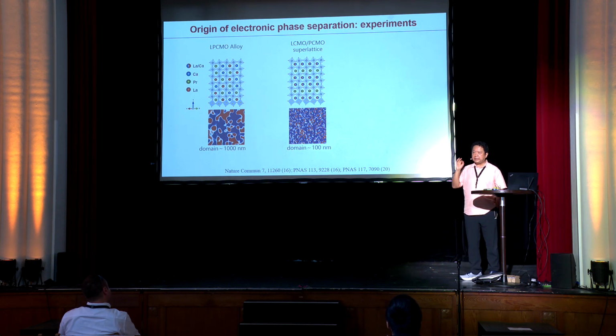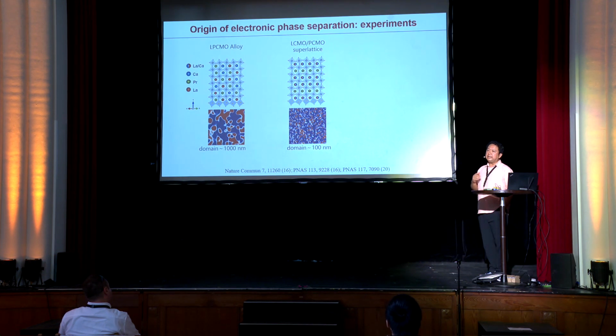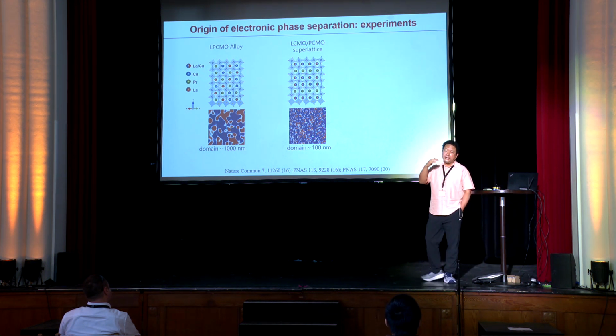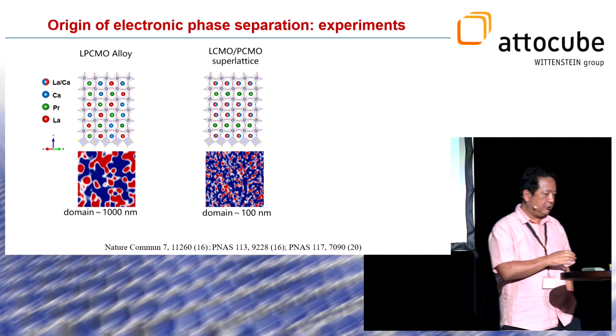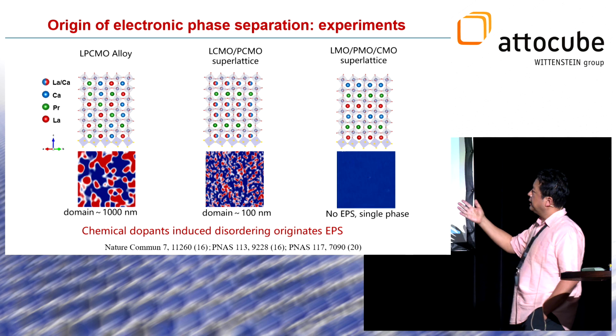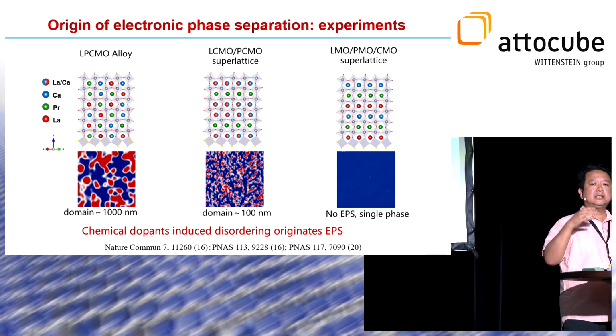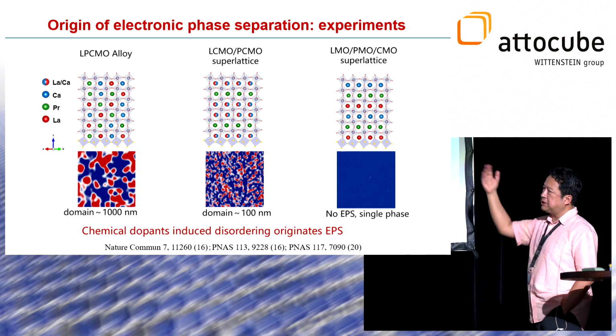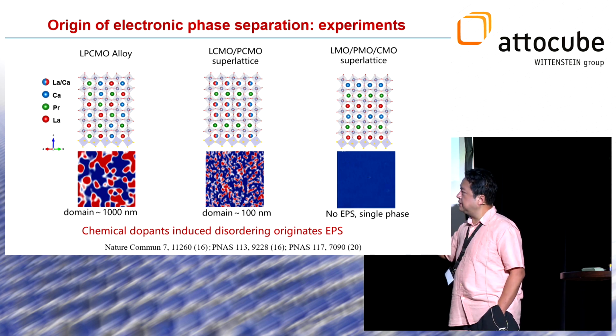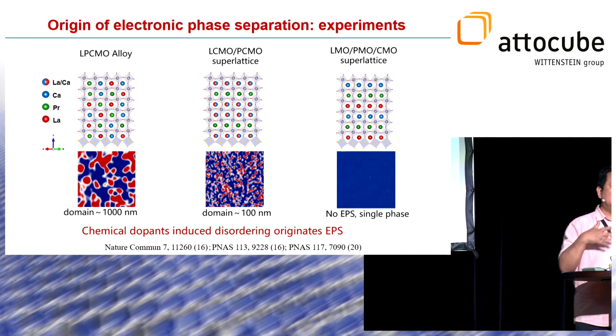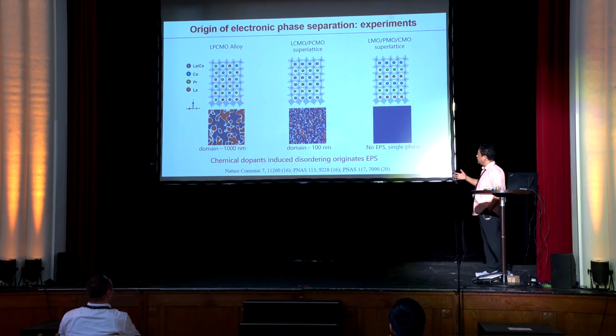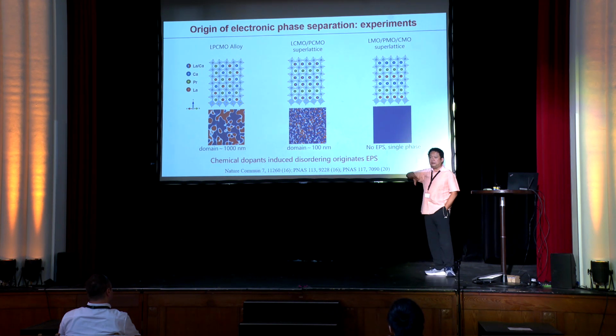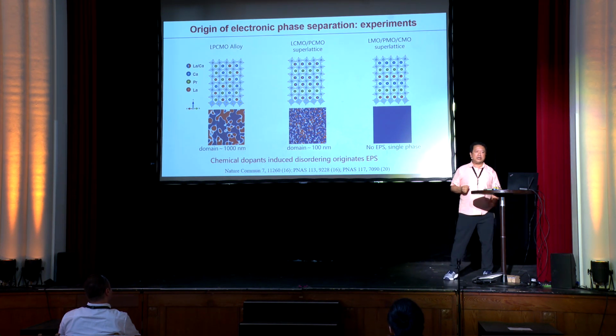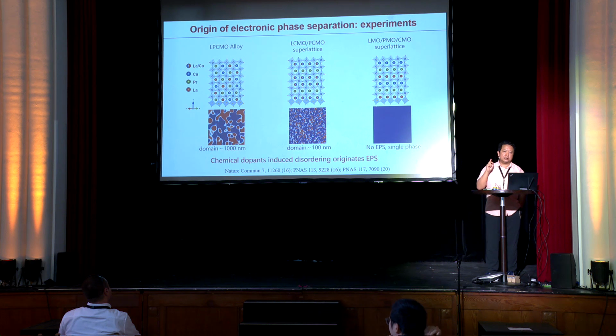We can also make this fully chemically ordered by making a monoatomically stacked superlattice: one layer of CMO, one layer of LMO, one layer of PMO. So now you have a fully chemically ordered system. All these lanthanum, praseodymium, and calcium dopants become spatially ordered. And what you see is that there's absolutely no electronic phase separation. The system becomes a single phase. Of course, you can apply a magnetic field to drive the whole system through a first-order phase transition from one phase to the other, but there's not going to be coexisting phases.